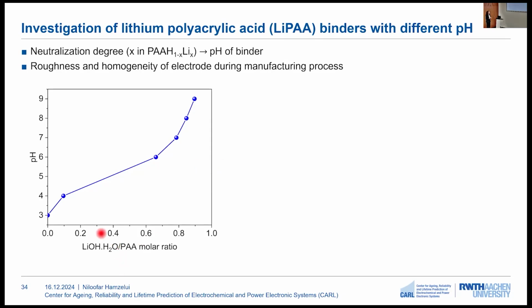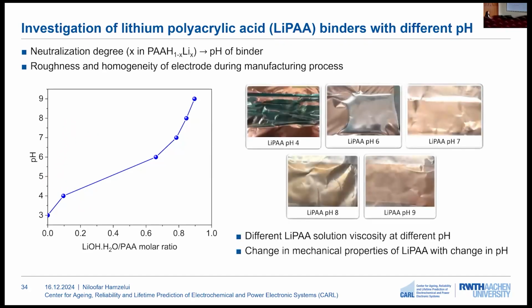Different ratios of lithium hydroxide to PAA were investigated, which is directly related to the pH of the binder. The binders were initially coated directly on top of the copper current collector, and after drying at room temperature, it was observed that the binder with a lower pH was delaminating from the copper current collector, and we can also see a change in color to blue-green. This effect is less pronounced at pH 6, and for pH 7, 8, and 9, we can see a transparent color of the binder and good adhesion to the copper foil.